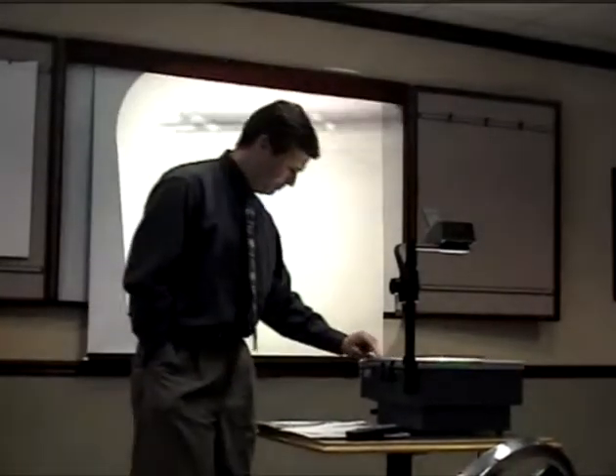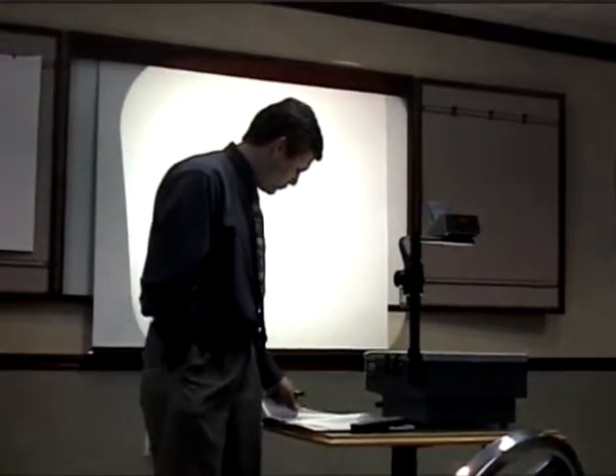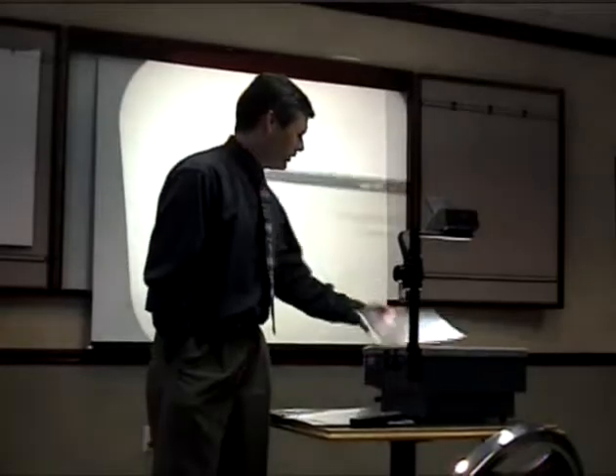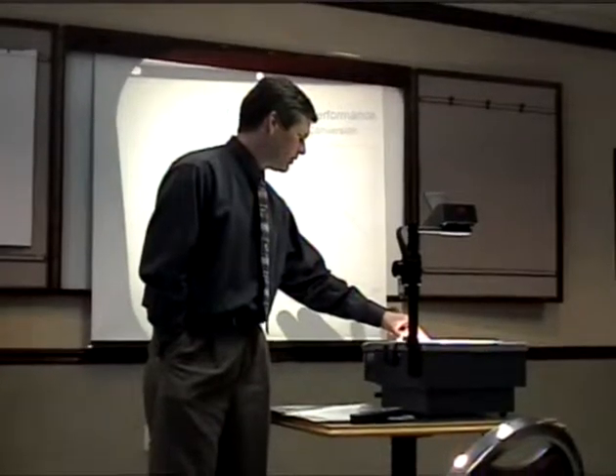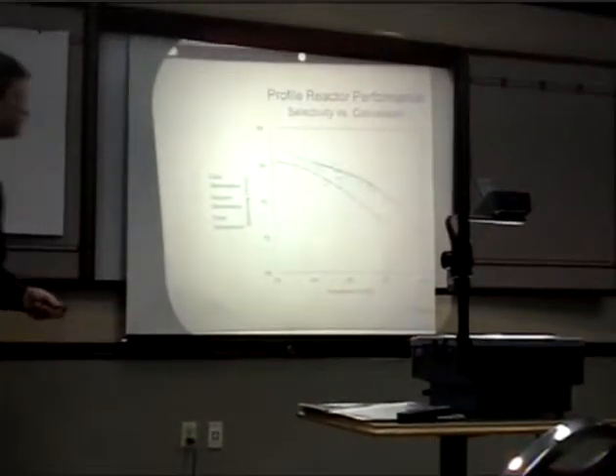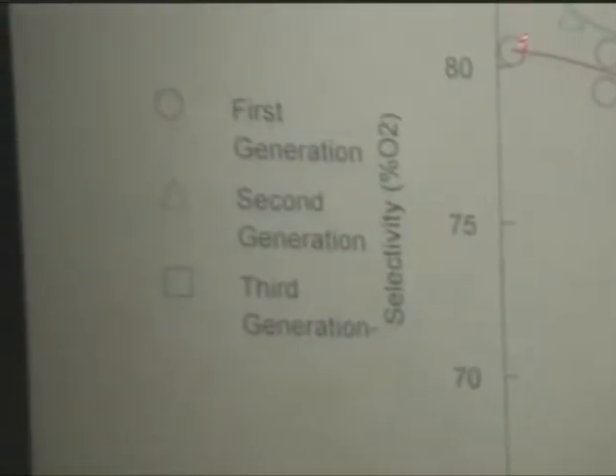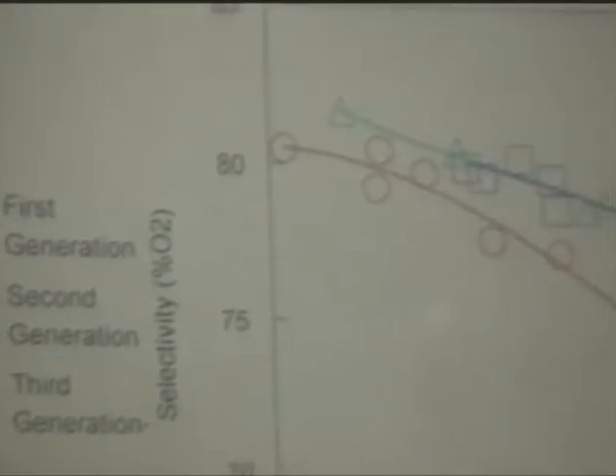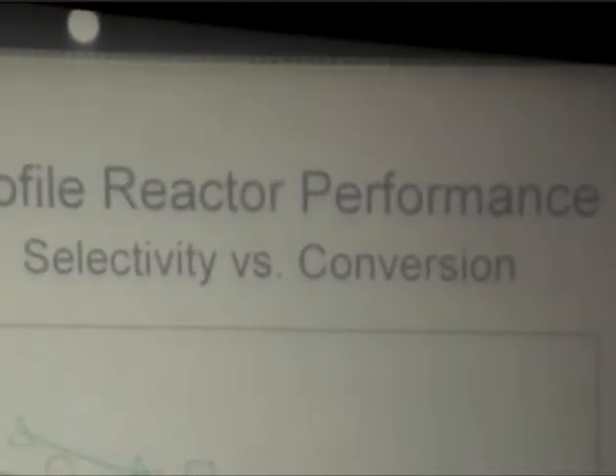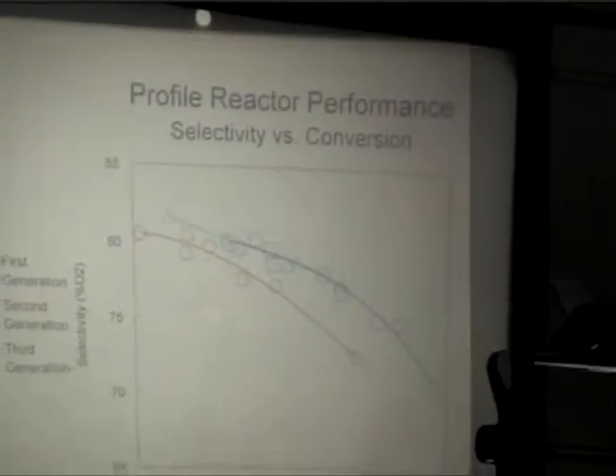And indeed, conversion is not so important unless you can have the selectivity. And so we compared the selectivity of these catalysts. And again, this is selectivity as a function of conversion profile. First generation catalyst, second would be the green, and then our third generation is at least as selective as a function of conversion as our second generation catalyst. So we were pretty pleased.